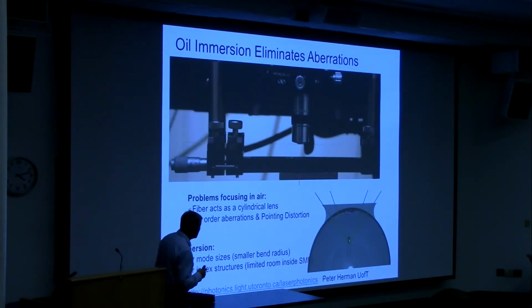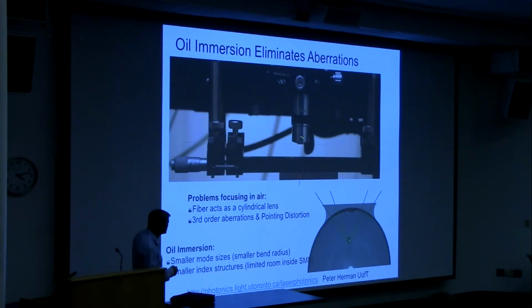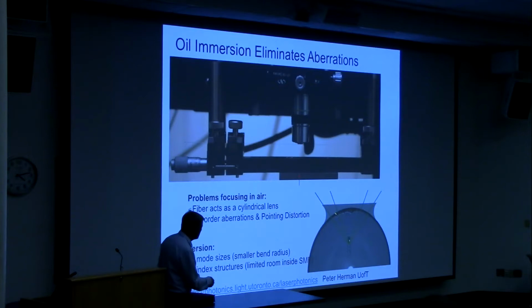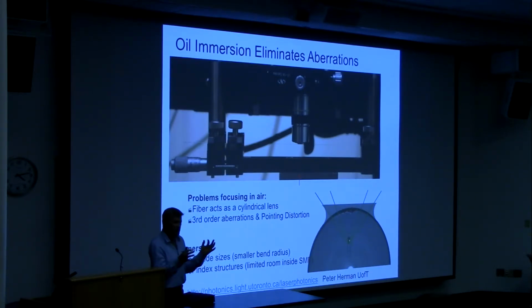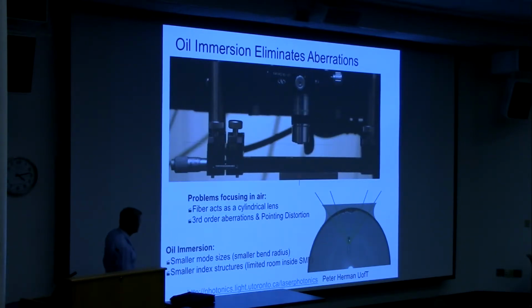So what we worked really hard developing was the use of an immersion lens. With an immersion lens, we use oils which have refractive index matched to this surface. It means that that surface disappears optically. So the laser can then be pointed anywhere in here without distortion, and guarantees that the focus has the same shape. Remember all those nonlinear effects I talked about? Well, we really dismantled those, and we're able to get reproducible modification anywhere in the area of the fiber from core to outside. So that was a really important development.